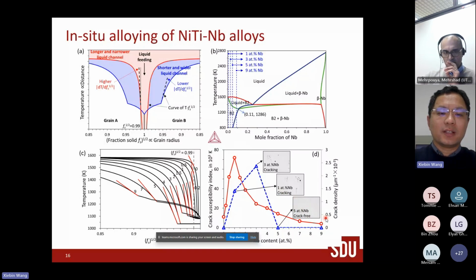And then based on this analysis, we did the experimental part. We use nickel titanium powders, which are pre-alloyed powders with a nickel content of 50.6%. And we use niobium elemental powders, which have almost the same size as the nickel titanium powders. After mixing, it looks very homogeneous. And we checked the particle size distribution and X-ray of the nickel titanium and niobium powders, and of course the transformation behavior. After adding niobium, the transformation temperature doesn't change, because niobium doesn't transform at temperatures between minus 150 and plus 150 degrees.